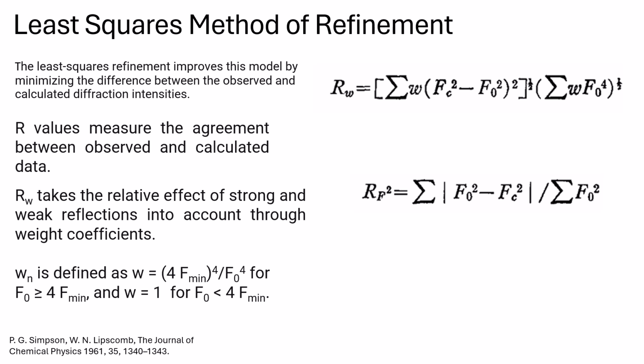Lipscomb proposed that the weight coefficients of strong and weak reflections could help find the difference in the residue more precisely. Since the strong reflections naturally have low relative uncertainty, they should have a lower weight to prevent them from dominating the refinement. And weak reflections have higher relative uncertainty and are prone to noise, but they contain critical information about minor electron density and bonding. As a result, different weight coefficients should be applied when we are doing refinement.